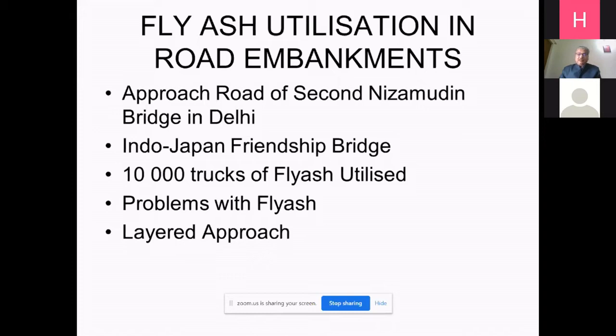So it cannot be transported in air. It cannot be stored without water. And considering this problem, mixing of the fly ash is also difficult. And you know the OMC of fly ash is more than 25%, while the OMC of other soils is around 8 to 12%. So it requires more water, and when it is having the water, you cannot mix it. For mixing, you have to dry it. And if you dry it, it will fly.